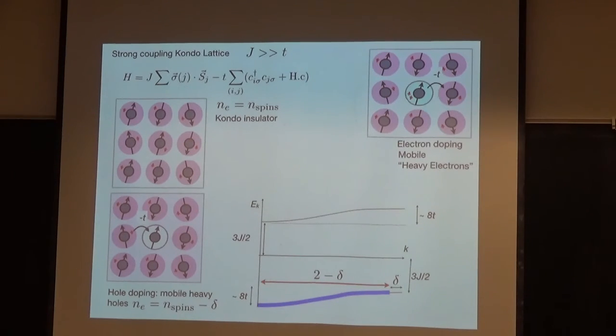Right, so the easiest way to do this would be to just pluck F electrons out, just replace them by a non-magnetic site, and that does indeed start to drive them metallic. Although I must say that the details of the metal insulator transition of Kondo insulators is very poorly understood. There is actually an iron-based version of this called iron silicide, which can be thought of as a kind of Kondo insulator.